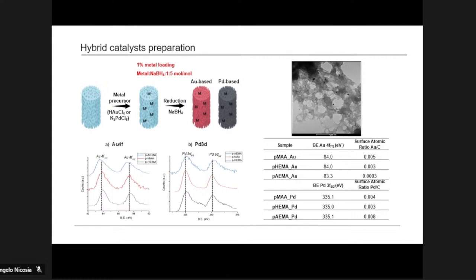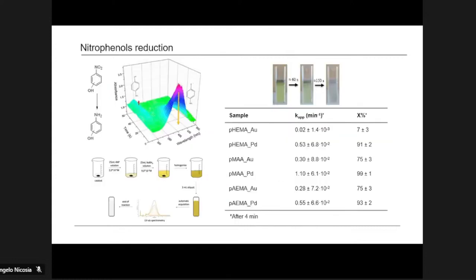The system was characterized by XPS spectroscopy to confirm the presence of the metal species inside the system, and TEM analysis to determine the dimension of the particles. We have obtained very fine nanoparticles in the range of 5-10 nanometers. So at this point, we have tried this type of material for the reduction of nitrophenol to aminophenol in the presence of sodium borohydride. Sodium borohydride is a hydrogen carrier to form hydrogen inside the system. It's a redox catalytic reaction, but we can follow it by UV-visible spectroscopy, and therefore correlate the absorption peak of the nitrophenol during the reaction with the kinetic performance, and therefore we can evaluate the properties of the final materials.